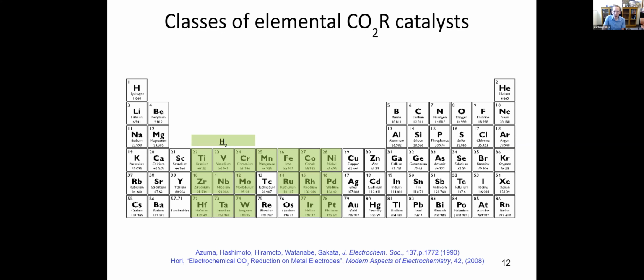And what the community has found is that if you make your cathode out of iron, cobalt, nickel, palladium, platinum, or any of these other materials, you generally bubble off a bunch of hydrogen. Cool if you want hydrogen for a fuel cell, bad if you want to turn CO2 into something more interesting. If you make your electrode out of zinc, gallium, silver, gold, you make CO. Also cool if you have a combination of CO and hydrogen, that's syngas. And I just told you that syngas can be selectively turned into other things. So that's also interesting, but it's not taking CO2 and making something really valuable.